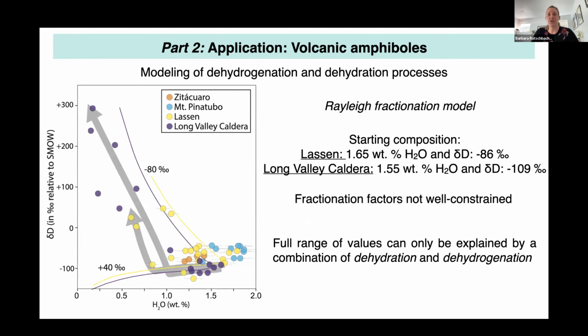And we can model the dehydrogenation and dehydration processes by using a simple Rayleigh fractionation model. So this is indicated here on the left by the yellow and purple lines. We chose slightly different starting compositions for Lassen and Long Valley because they crystallized from compositionally different magmas. And I have to point out that fractionation factors are not very well constrained experimentally. But if you take what is published out there, you can basically come up with what is shown on the left. And what that means is that we can only recreate the full range of values by a combination of dehydration and dehydrogenation. This is illustrated by the gray arrows here. So in a geological context, we think that dehydrogenation is happening to the amphiboles after crystallization in the magma reservoir, but prior to eruption, probably during heating by incoming mafic magma. And then once they're mobilized and sent towards the surface and erupt, they experience dehydration. So it's a combination of both processes.